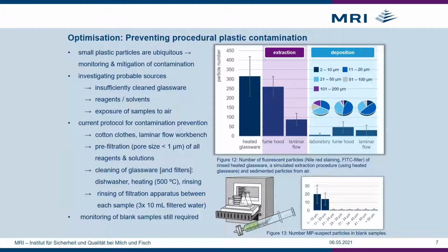Nevertheless, even with the most thorough measures for contamination prevention, plastic suspect particles with diameters in the lower micron range were still observed in blank samples. This emphasizes that monitoring of blank samples during sample preparation is recommended.